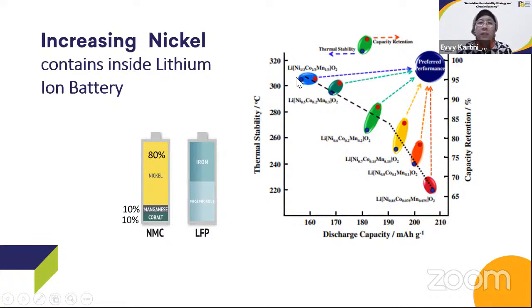Yeah, but it has good thermal stability. But increasing the nickel content increases the specific capacity. Of course, the thermal stability also decreases, and also the capacity retention. But there are many studies to improve the capacity retention, for example, using rare earth materials, adding graphene, and several coating and doping materials. They're still undergoing. However, the 811 has become the prima donna, the future of the battery component in the car.